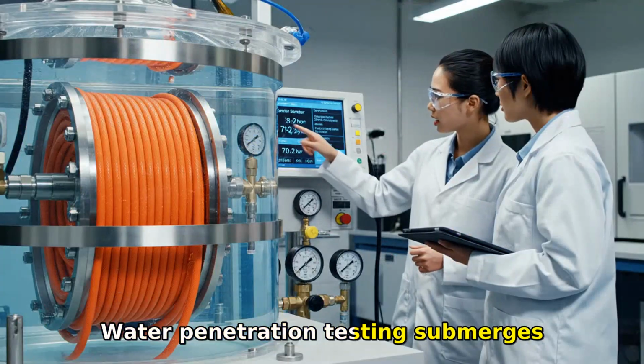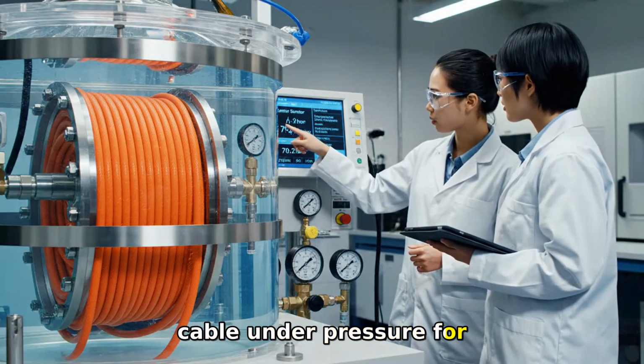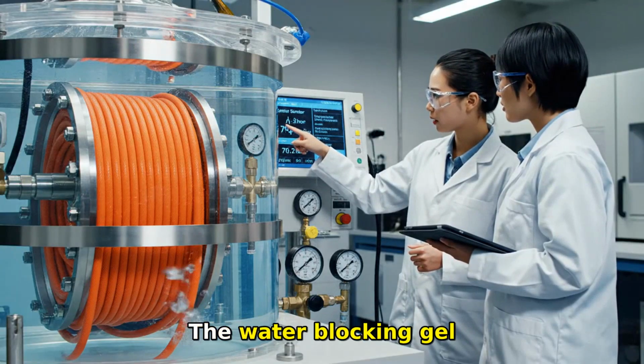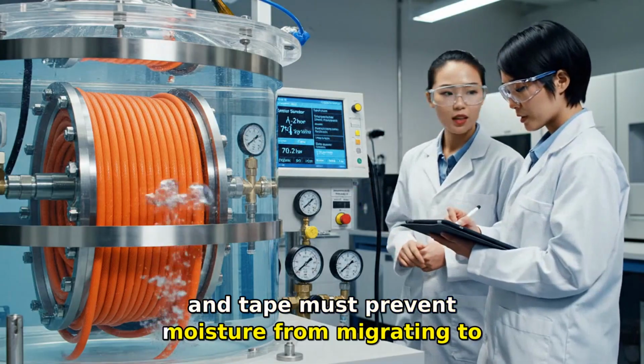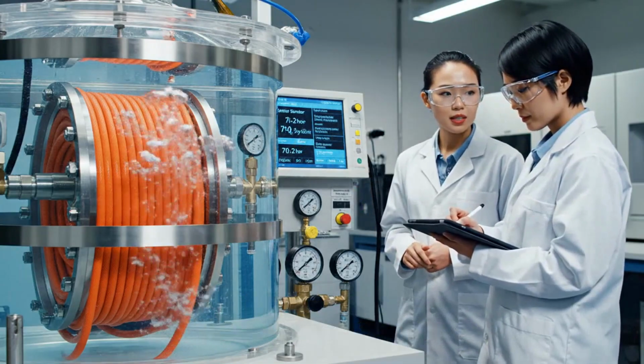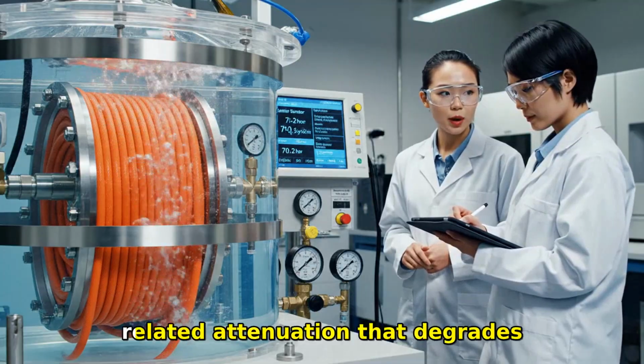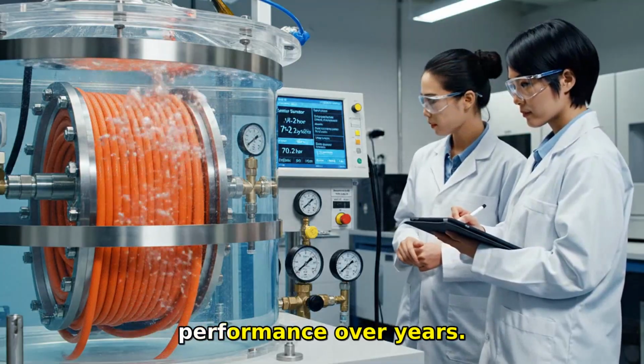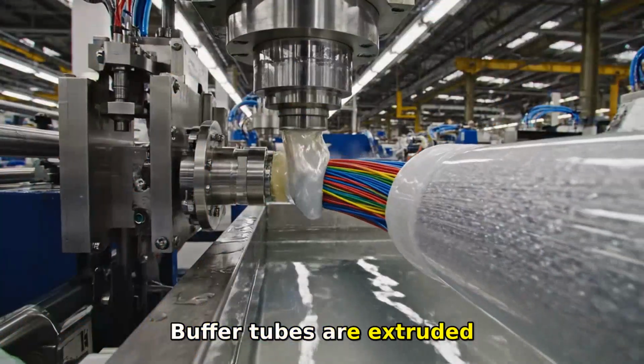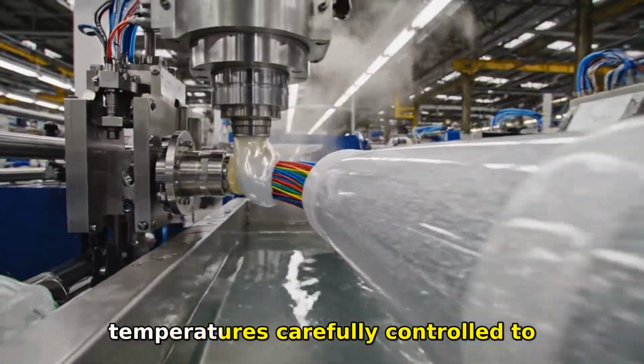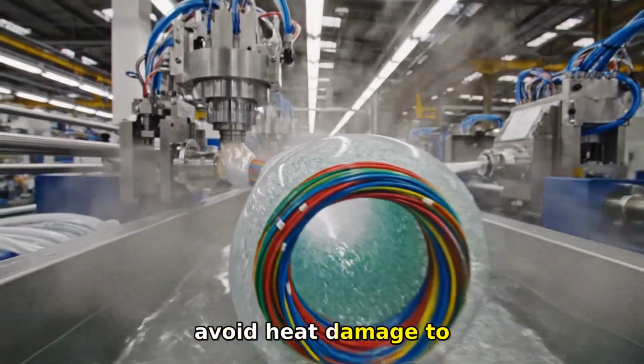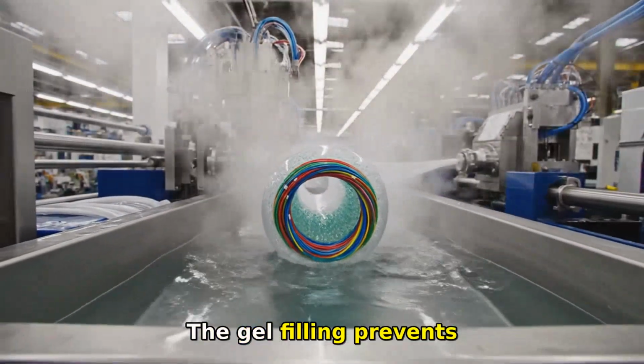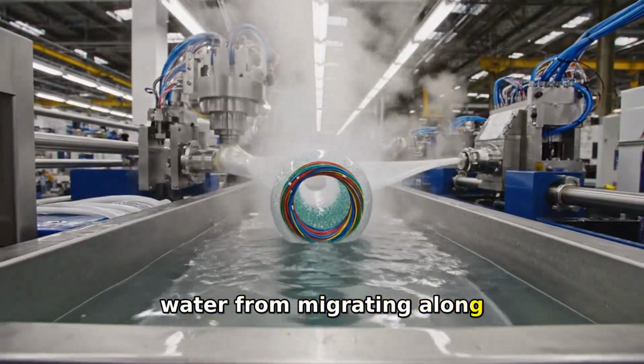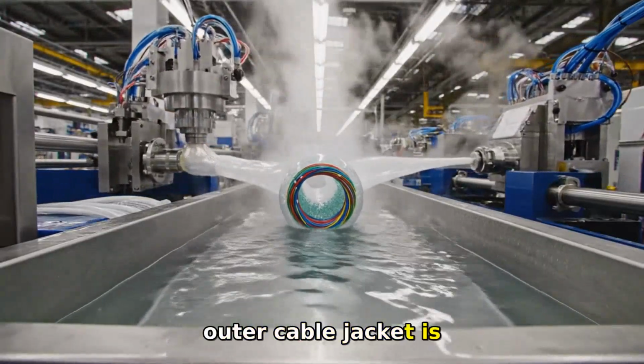Water penetration testing submerges cable under pressure for 72 hours. The water-blocking gel and tape must prevent moisture from migrating to the fibers. Any ingress causes hydrogen-related attenuation that degrades performance over years. Buffer tubes are extruded around fiber groups at temperatures carefully controlled to avoid heat damage to the coatings. The gel filling prevents water from migrating along the tube if the outer cable jacket is breached.